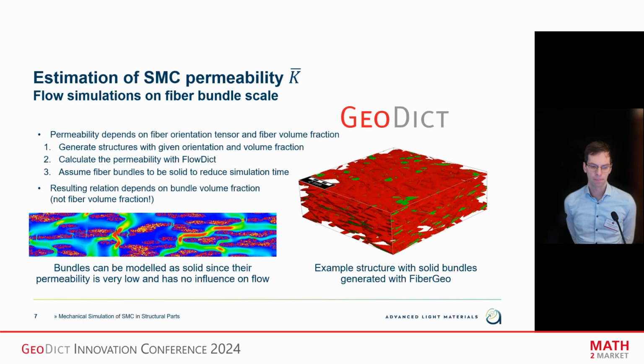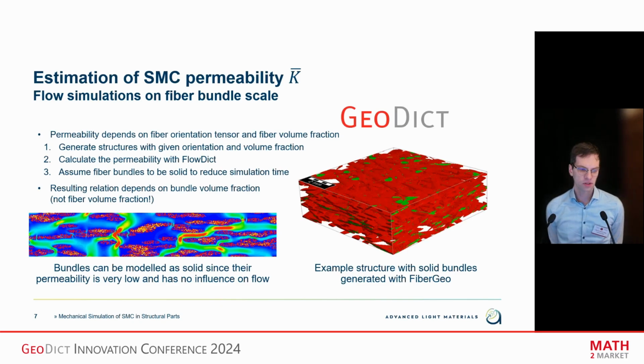And this is the first study we did then in GeoDict on structures generated with FiberGeo. We generated structures with given orientation and volume fraction, calculated permeability, and then deduced formulas for the permeability as a function of fiber orientation and fiber volume fraction.